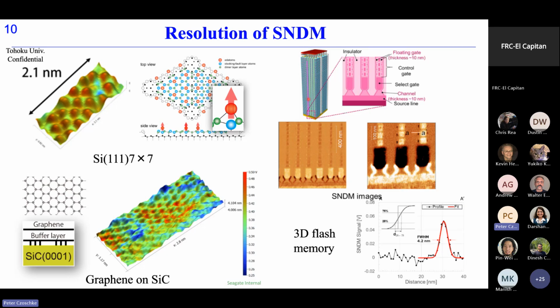And also, this SNDM is applicable to evaluate or measure the carrier or dopant profile of the very tiny semiconductor device. This is a cross-section of the three-dimensional flash memory. You can see the surrounding gate is here, and also this line profile was taken along this prime line on the surrounding gate. And so we can resolve the very small carrier profile with a resolution of the 1 nanometer order. So SNDM is applicable for the state-of-the-art next generation semiconductor device designed by using the nanometer scale design rule.